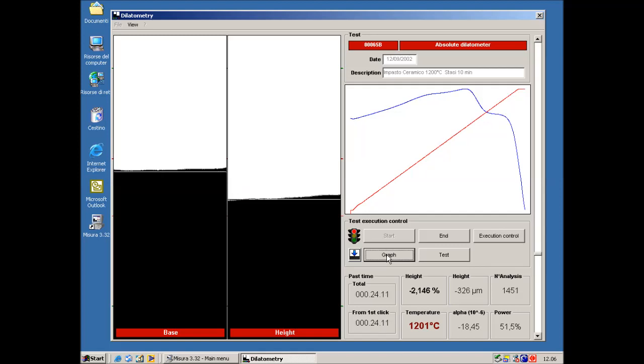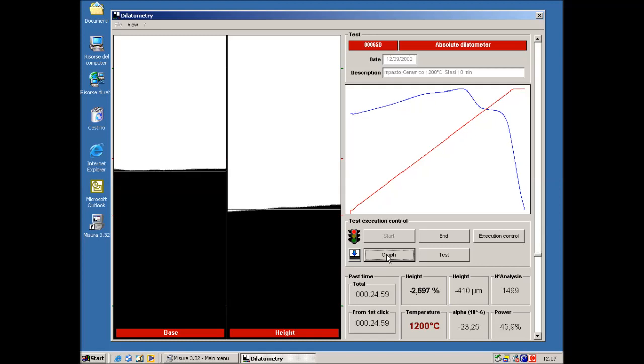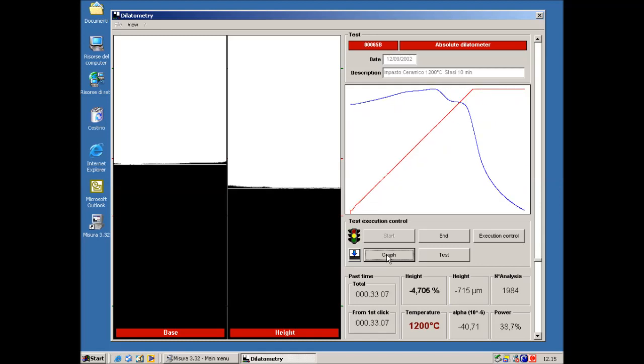The interval at constant temperature starts when the temperature reaches 1200 degrees C. Note that the temperature of the kiln overcomes the set point by only 1 degree. The sintering process continues even during the permanence at constant temperature, but the speed of sintering is progressively reduced. At the end of the permanence at 1200 degrees, the cooling starts, and the temperature drops very quickly. The height of the sample keeps reducing because of the thermal contraction caused by cooling.